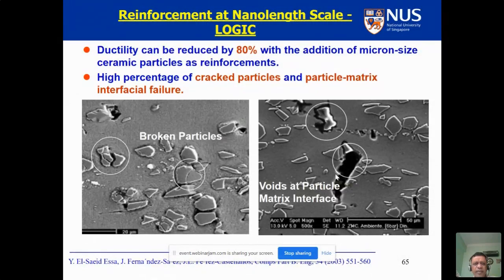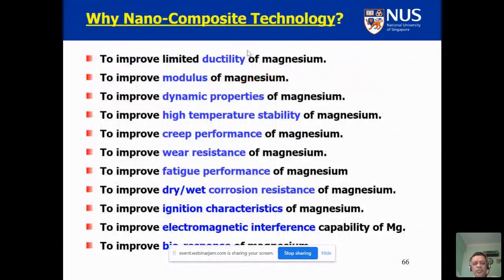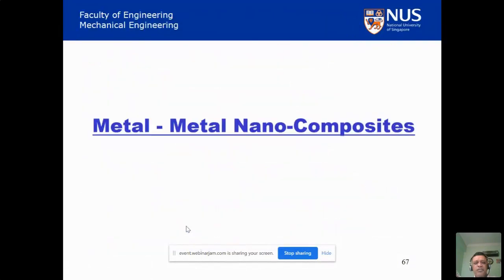So why do we use a nano length scale reinforcement? For a very simple reason: if you use a micron length scale and you apply the load, the particle will break or they will debond. And if that happens, then that's a site of crack initiation, then the crack will propagate and you will compromise on the strength, ductility, which can be compromised up to 80%, and the toughness. So you'll have very low toughness. We don't see these issues with the nano reinforcement. And in case of magnesium, we have seen from all the work we have done that you can improve the ductility, modulus, dynamic properties, high temperature stability, creep properties, wear properties, fatigue properties, dry and wet corrosion resistance, ignition, electromagnetic interference capability, and also the bioresponse of magnesium.